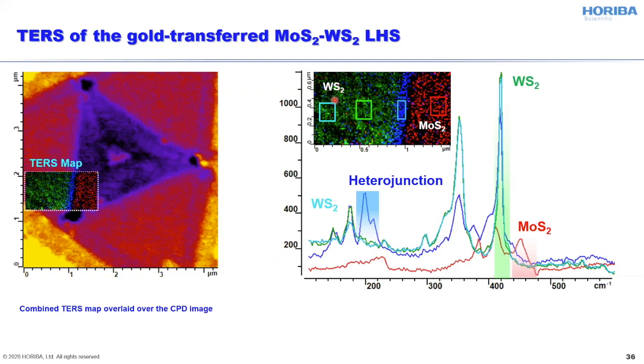So this observation actually made me very happy because, first of all, I was able to do it at all. This result, by the way, was obtained exactly a week ago, which is nice. And also it showed that the spectral features that we observed in the transition area between the molybdenum disulfide and tungsten disulfide in prior samples were not strictly sample specific. They are more general, and that gives us hope that at some point we will understand perfectly well which exact vibration these peaks correspond to and how to assess the composition of this transition area by the position and the intensity of these specific peaks.